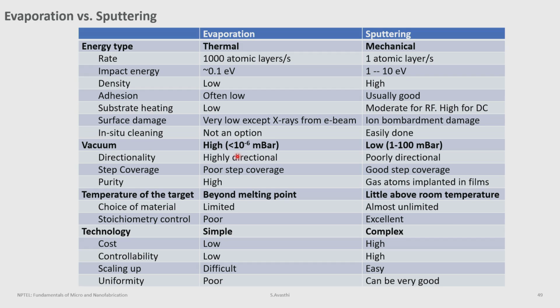With that, let me put up one slide of comparison between evaporation and sputtering, because this is a decision that you often have to make, which one to choose. The energy type in evaporation is thermal. In sputtering, it's mechanical. The rate in evaporation can be very high. Sputtering tends to be a little lower. However, the impact energy of evaporation is very low. Sputtering is a little higher, which allows you to get the same quality of films at much lower temperature, just like we discussed in the Thornton diagrams.